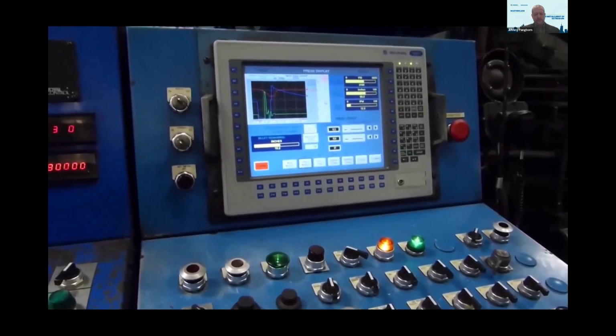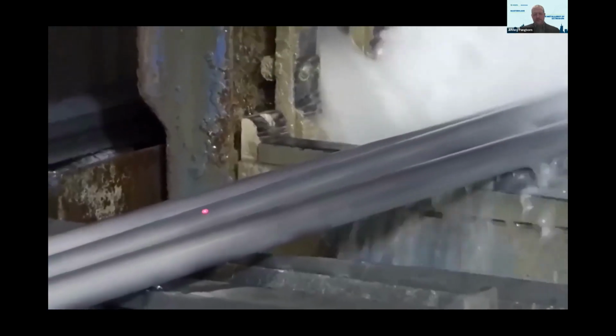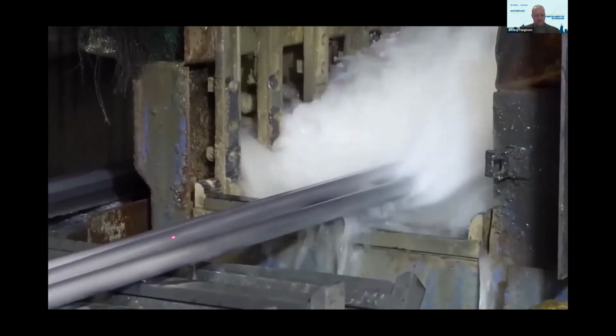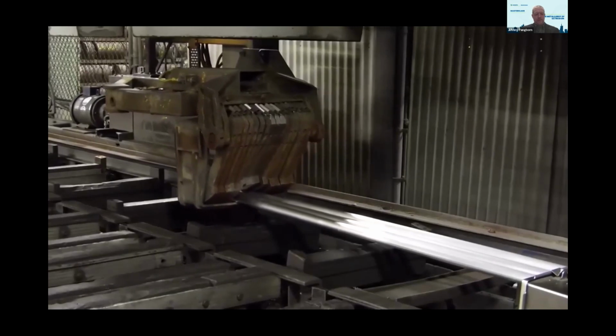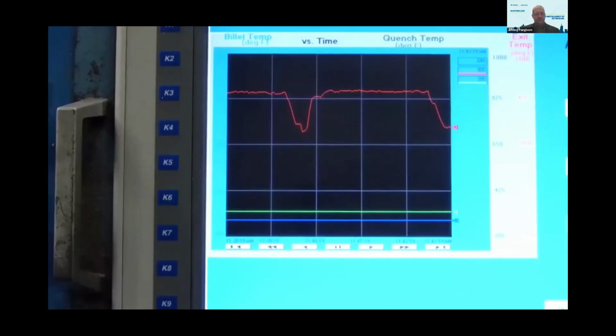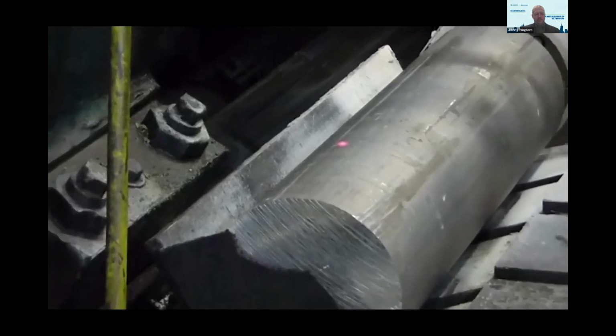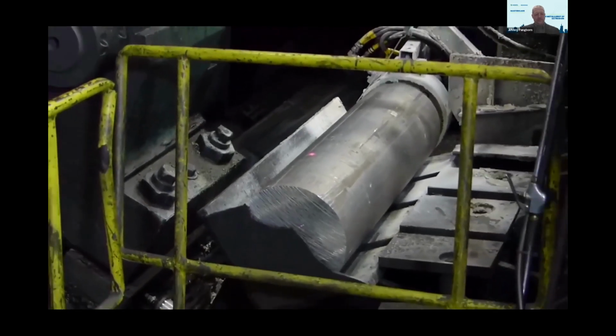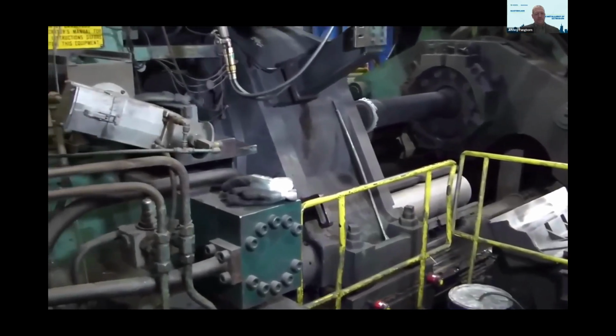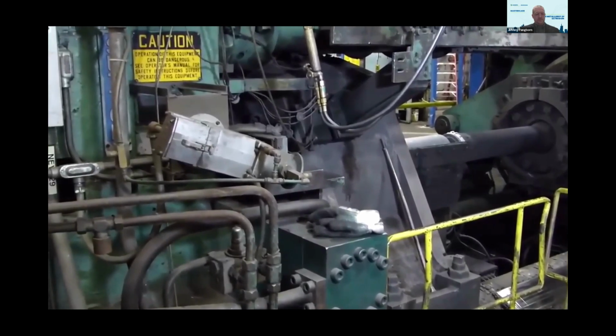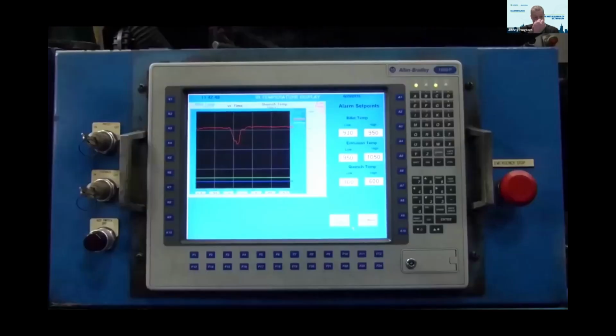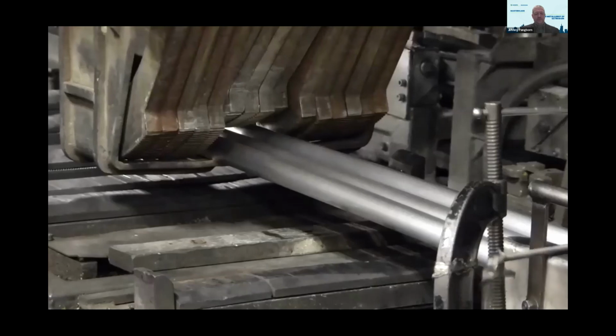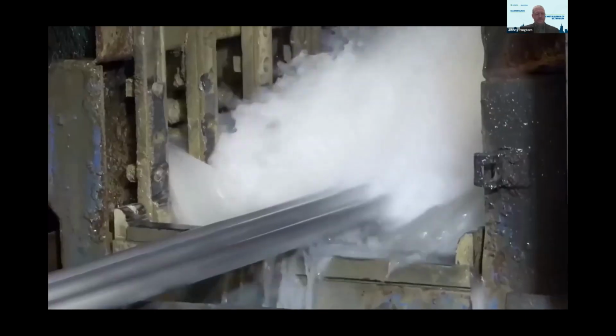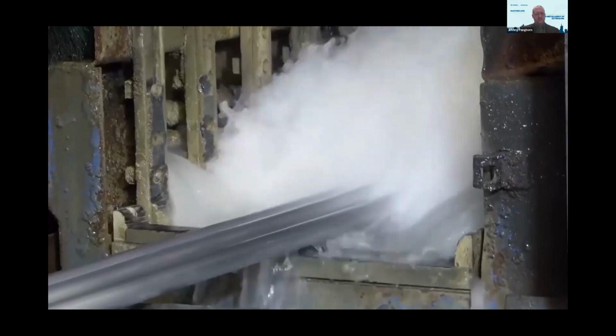Let's take a closer look at the importance of temperature and process controls throughout the extrusion run. Controlling the heat of the alloyed aluminum as it moves through production is a critical success factor that requires a number of variables to continuously align with one another. We've already discussed the heating of the billet to a malleable temperature, but you should also know that the container, extrusion die, and other support tooling are also preheated to temperatures that allow the aluminum operating temperature to be maintained at desired levels throughout each push. If these process components aren't precisely controlled within their specified temperature ranges, the operating temperature of the aluminum will be impacted by those components, either by adding to or absorbing from heat required for solution heat treatment.